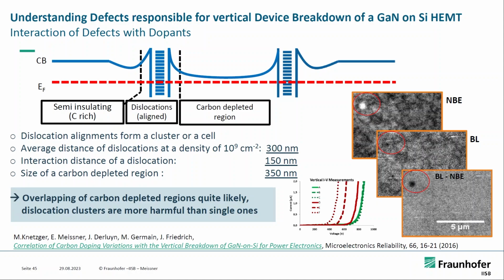So what you find, if you make photoluminescence, is that we observe the near-band emission, we observe the blue luminescence, and we make differential pictures, and the blue luminescence can be associated with the carbon concentration.